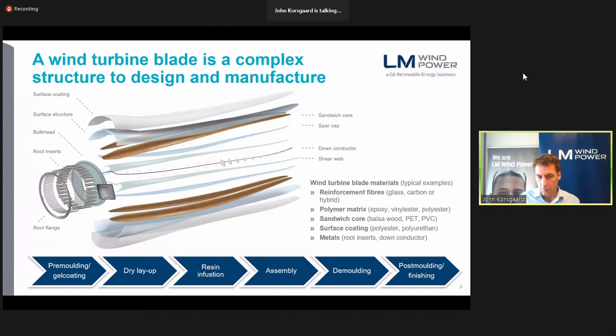Then after that we go to the resin infusion. It should state resin infusion, where the dry layup is covered by a thin plastic foil and the resin is infused under vacuum. So the process that we apply is vacuum assisted resin transfer molding, VARTM in short.